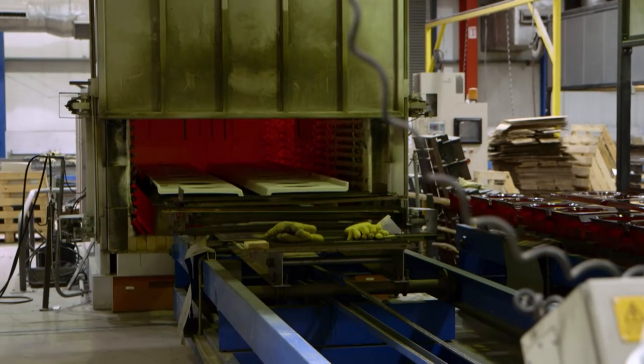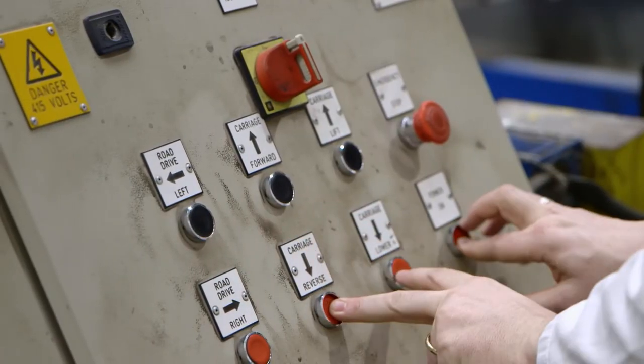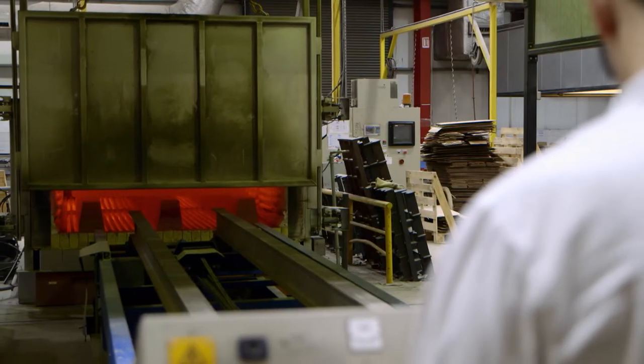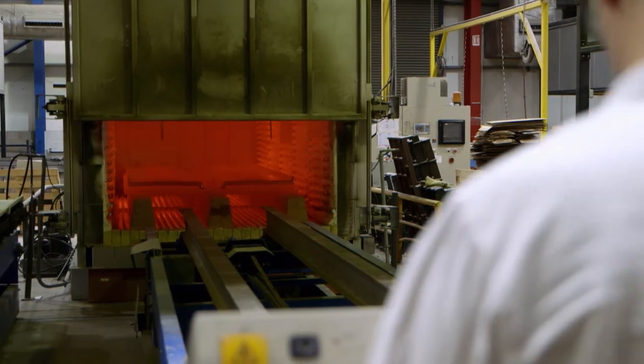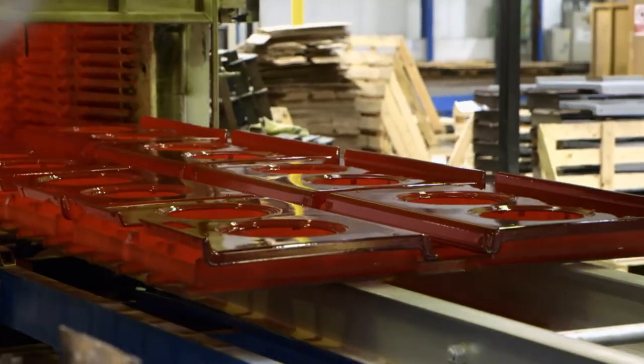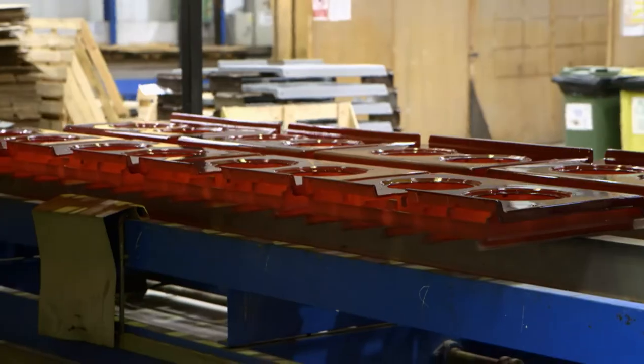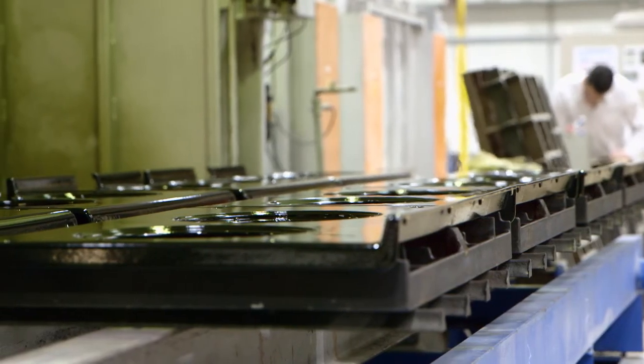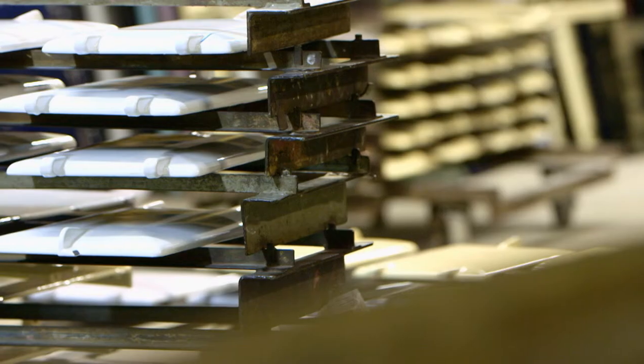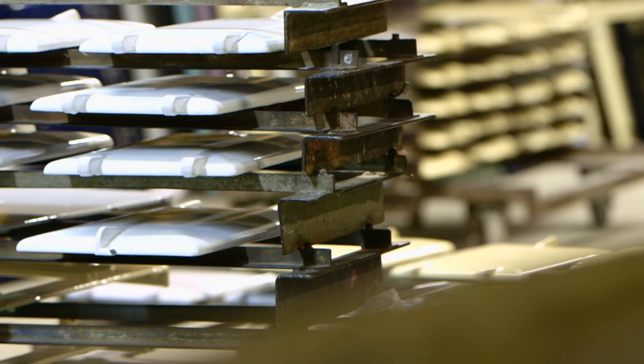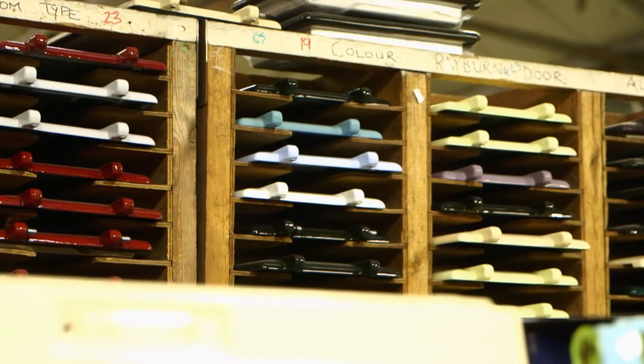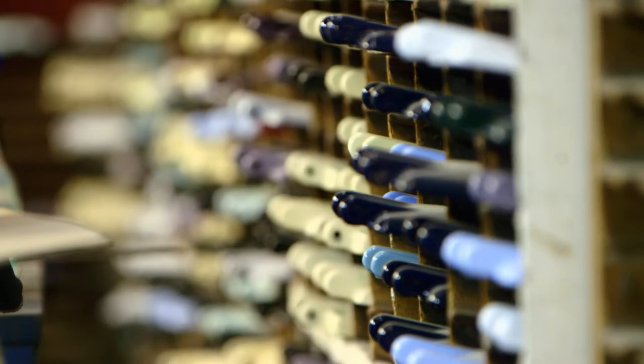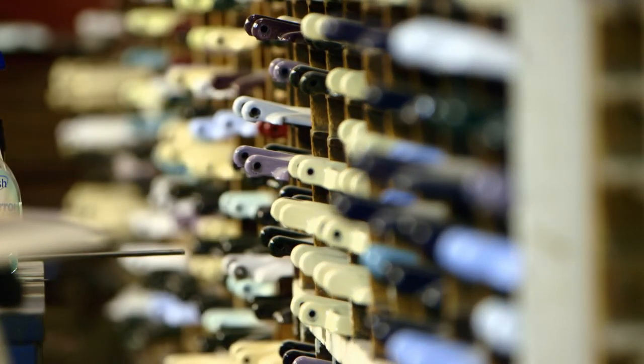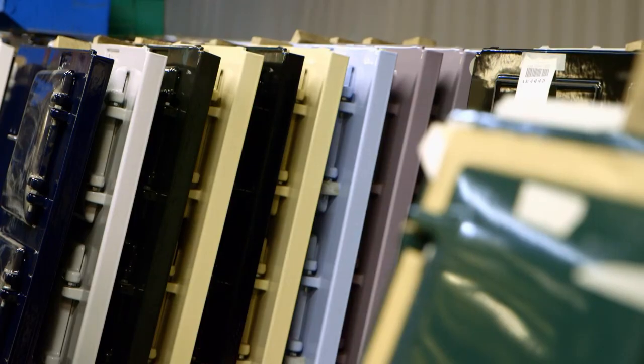Enamel is made up of tiny particles of glass and is sprayed onto the cast iron. It is then baked in a furnace at 800 degrees Celsius until it is literally red hot. This fuses the enamel onto the cast iron. This process is repeated 3 times to produce a smooth, high gloss finish, which is very easy to keep clean. The parts, doors and tops are all color matched for each individual model.